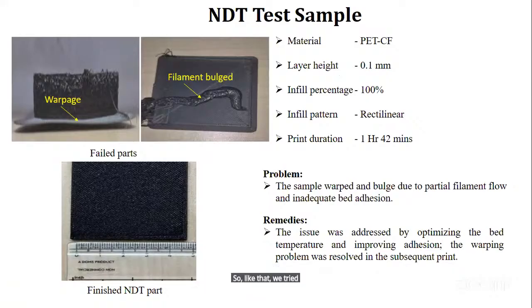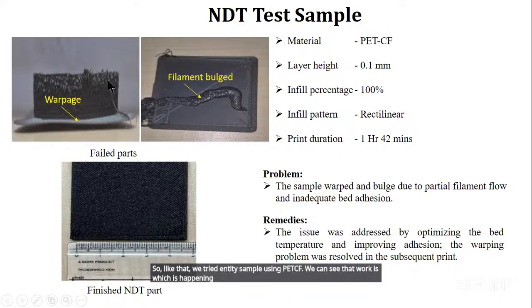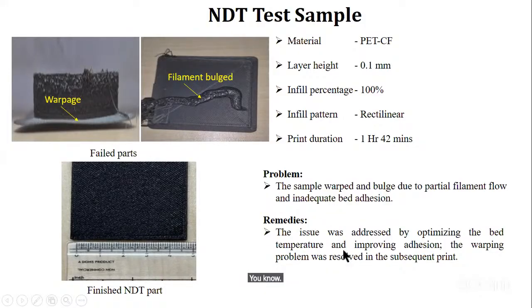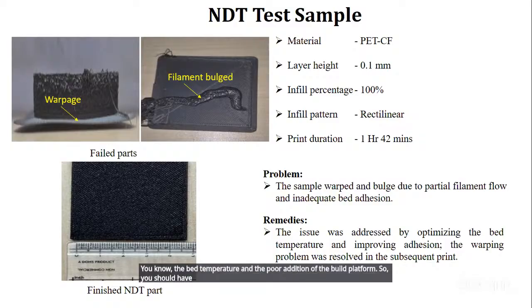Like that, we tried an NDT sample using PETCF. We can see the warpage which is happening, and also stringing and all those things, and filament bulging for this PETCF. The problem was that this warpage and bulge is due to the bed temperature and the poor adhesion of the build platform. So you should have the proper bed temperature also to avoid this bulging and warpage of the sample. So finally, we printed the proper one after changing the bed temperature.